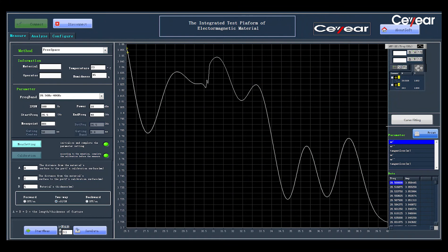Then, we can get the result trace at the right and the digital value at the bottom. You can see the quartz glass dielectric constant is between 3.7 and 3.8 from 18 GHz to 40 GHz. The result is identical to each widely accepted value.